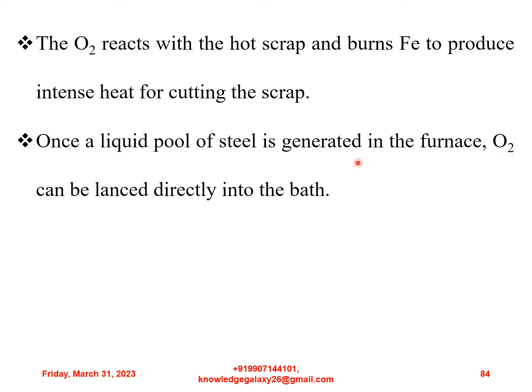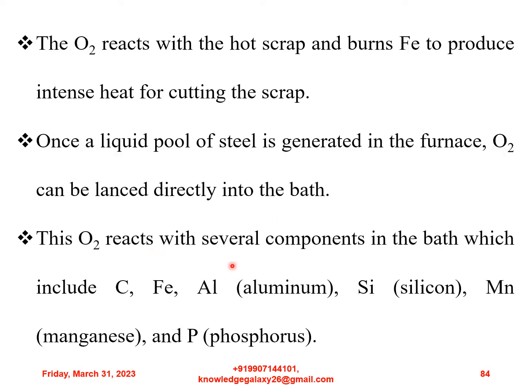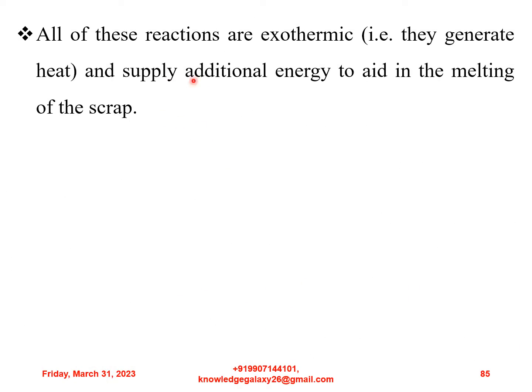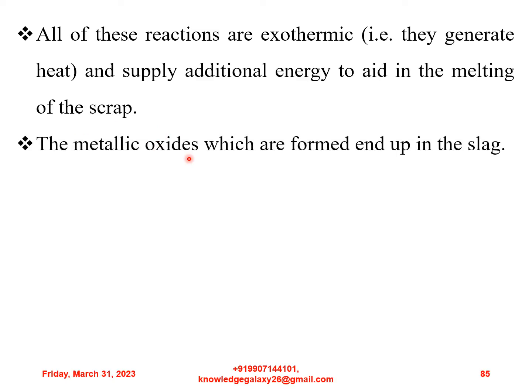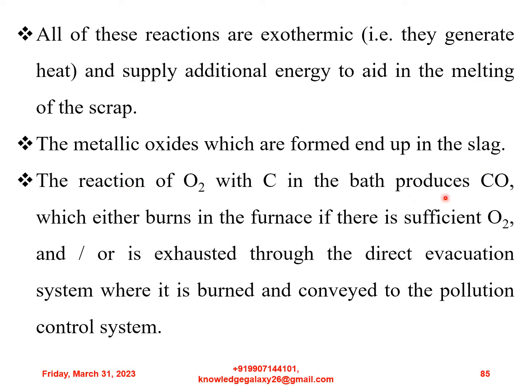Once a liquid pool of steel is generated in the furnace, oxygen can be lanced directly into the bath. This oxygen reacts with several components in the bath which include carbon, iron, aluminium, silicon, manganese and phosphorus. All of these reactions are exothermic in nature, that is, they generate heat and supply additional energy to aid in the melting of the scrap. The metallic oxides which are formed end up in the slag. The reaction of oxygen with carbon in the bath produces CO, that is carbon monoxide, which either burns in the furnace if there is sufficient oxygen or is exhausted through the direct evacuation system where it is burned and conveyed to the pollution control system.